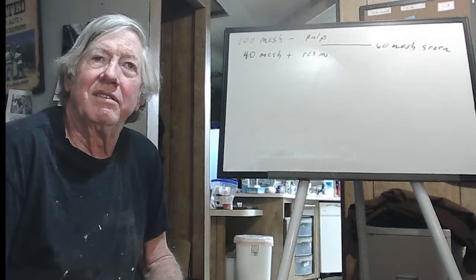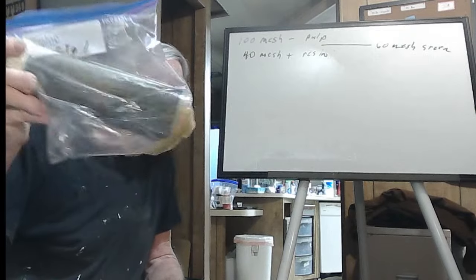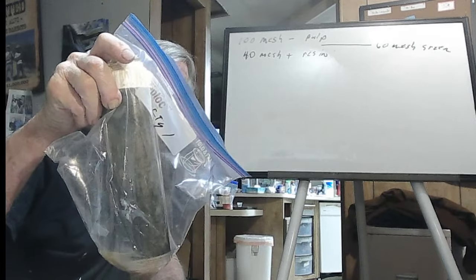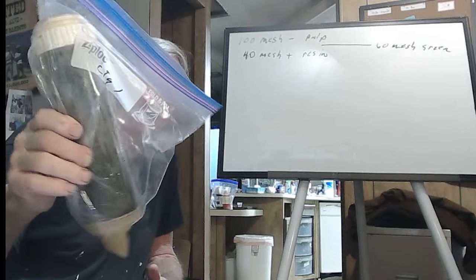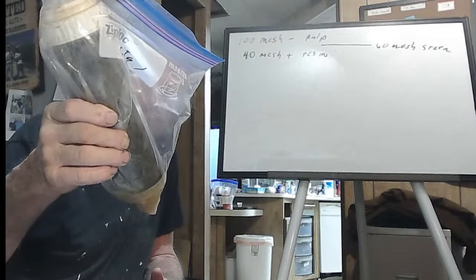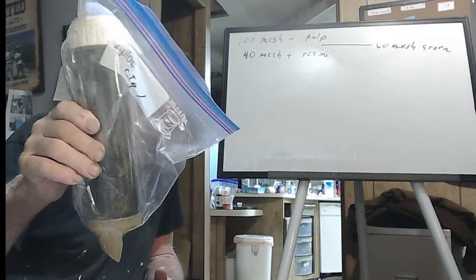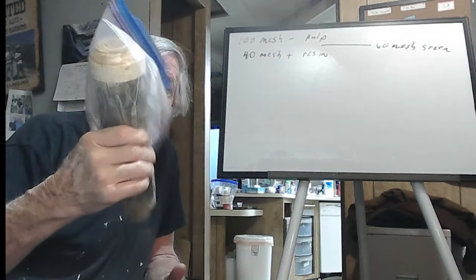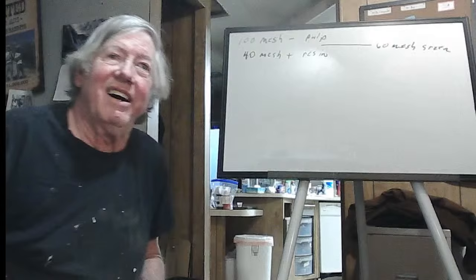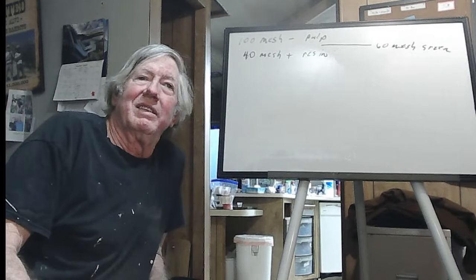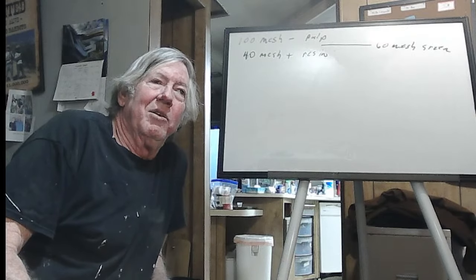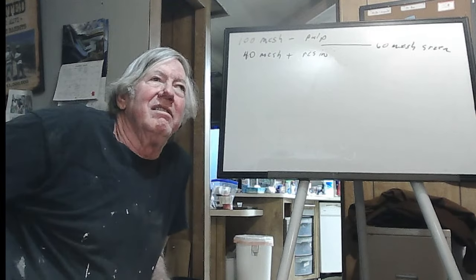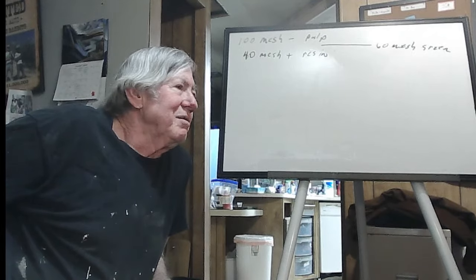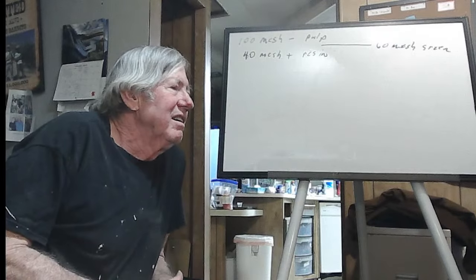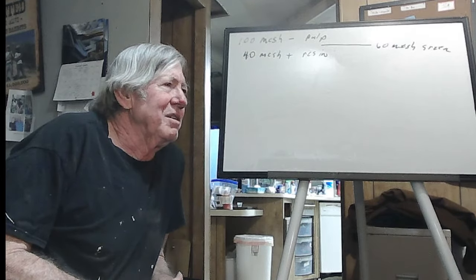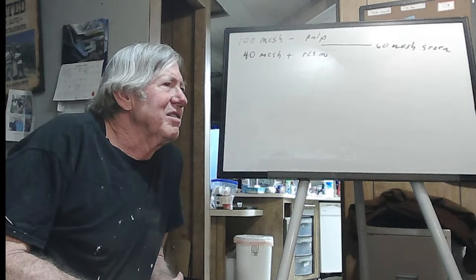The negative is that we have not been able to successfully regenerate this. In theory, you should be able to take this resin, get the gold off it, clean the resin back up again, get rid of other stuff that it's got stuck to it, and turn it back to pretty effective resin. And you should be able to do that multiple times. So far, we have not found out how, but it's not hugely important. In terms of, did we ever figure out how much we were actually stripping from there?